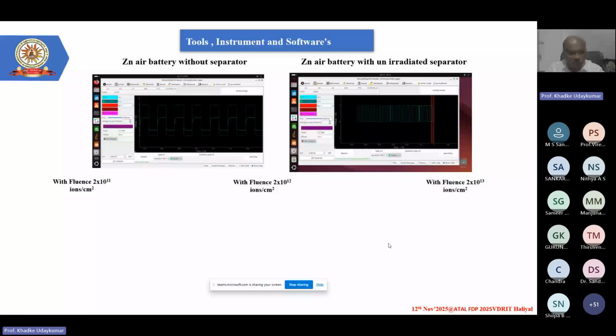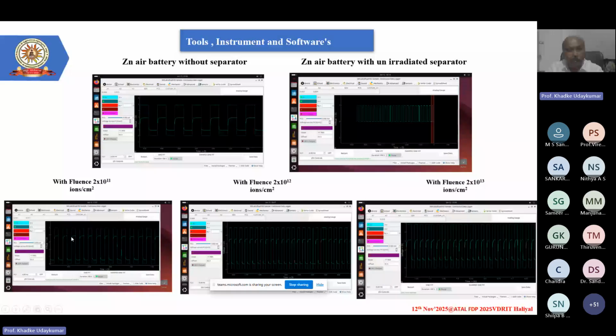Here you are giving the voltage, and how much charging is taking place can be understood on the screen. These are all shown with and without the separator. The first one is without the separator; the voltage is going half the way. Then the same separator, completely unirradiated: with the separator without irradiation there is a sudden increase and sudden decrease in the voltage, no passage of current is taking place, no power. When you irradiate it with 10 to the power 11, you can see a drastic sudden increase in the voltage, and current is also moving, in the sense that there is a movement of ions. These graphs show how the voltage variation is taking place. Voltage reduces, meaning it is utilized to move the ions.